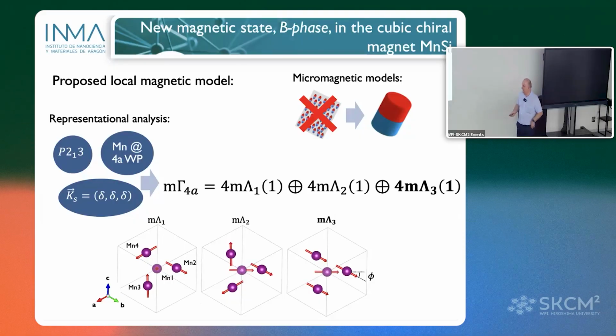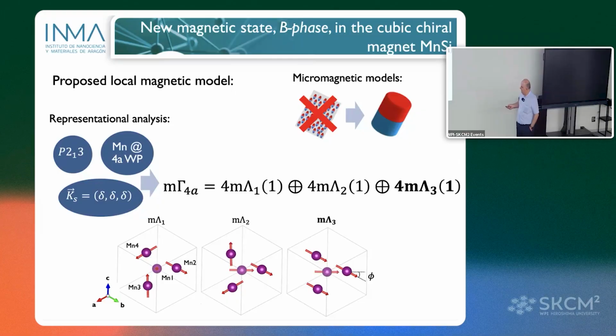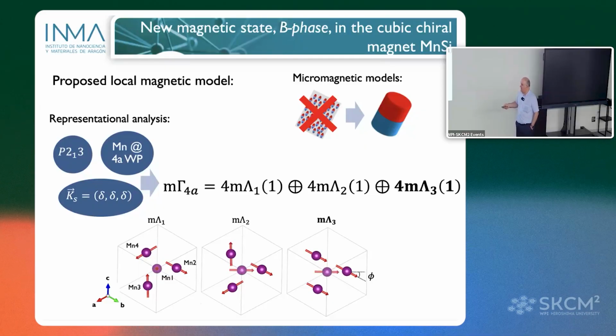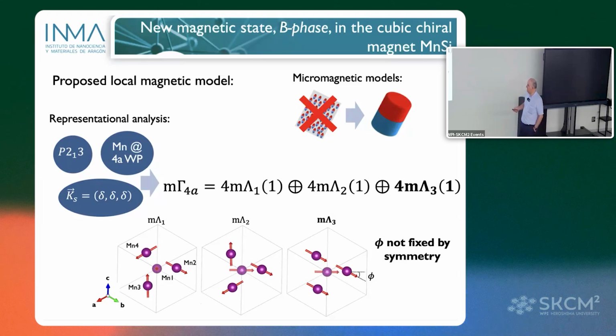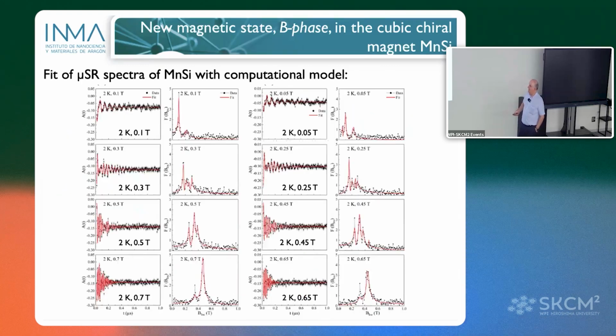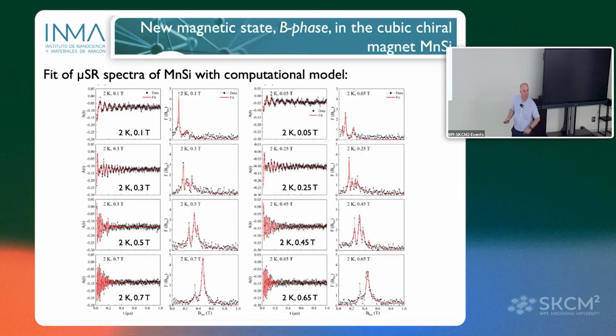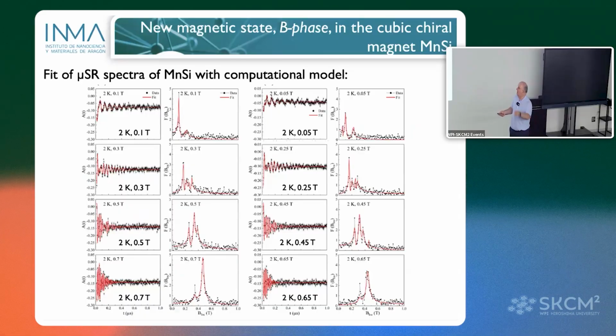And then with muons, I mean we were playing with this angle because this was a model to explain our muon data by allowing the variation of this phi angle. This was not possible, and this was not possible. And then only by moving one parameter, the phi angle, we were able to fit all the data at 2 Kelvin, up and down.